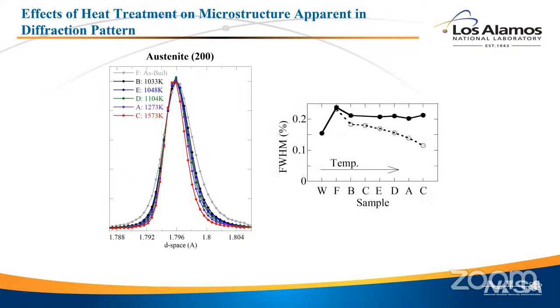And if you plot that as a function of the heat treating temperature, in order, you see how the peak width drops off as the temperature is increased. These solid black lines are what the peak width was to start with, and the open lines are after the heat treatment. So that change is a signal of how much dislocation annihilation, how much recovery we've had.